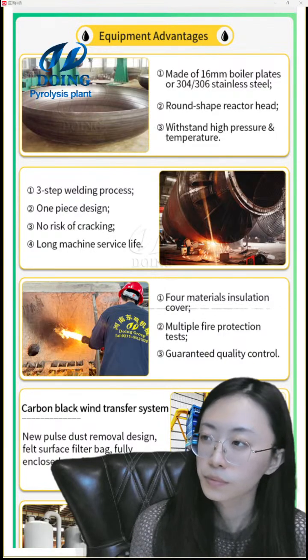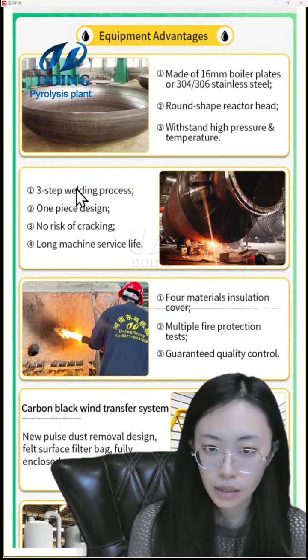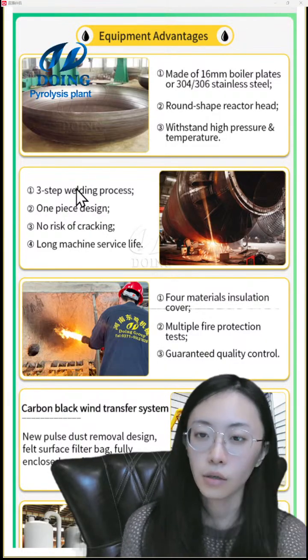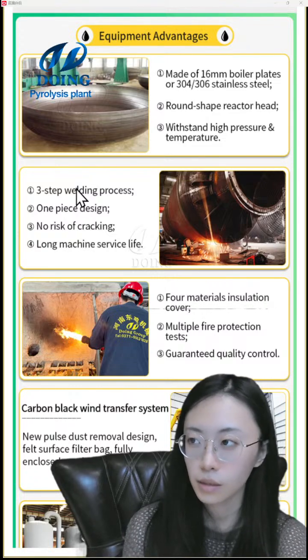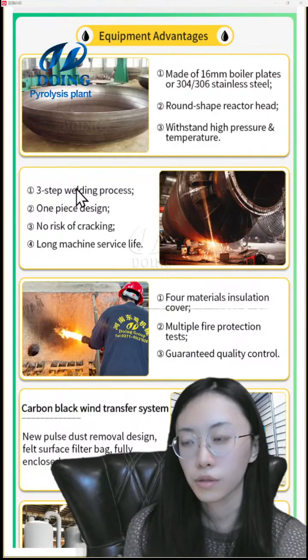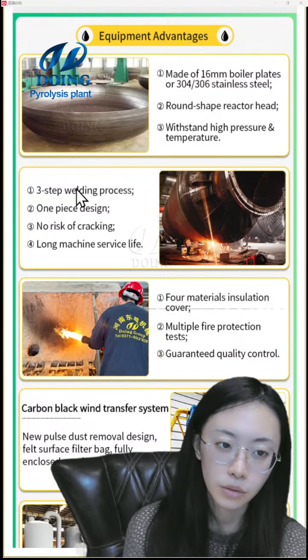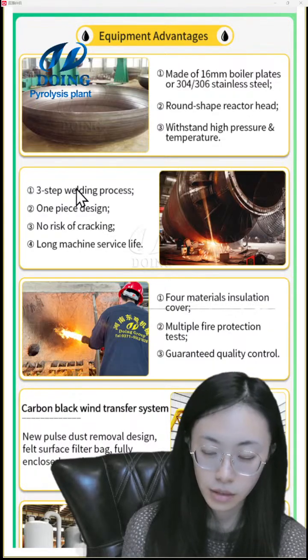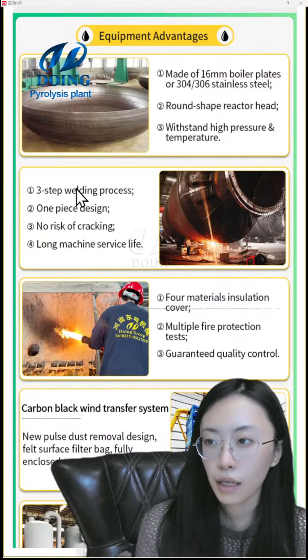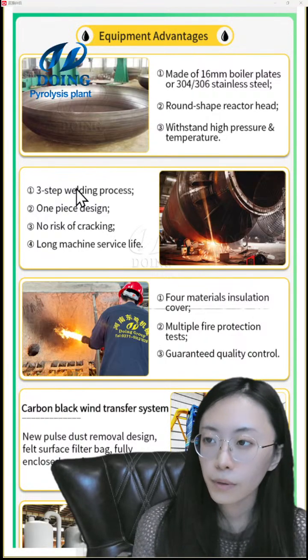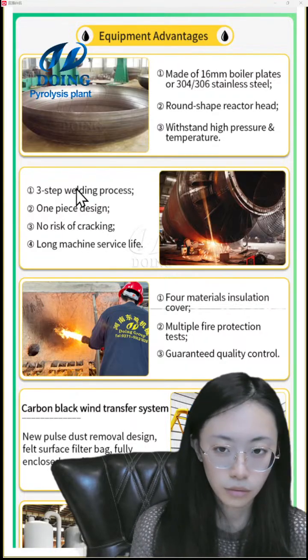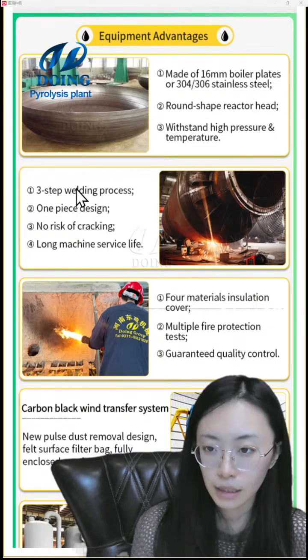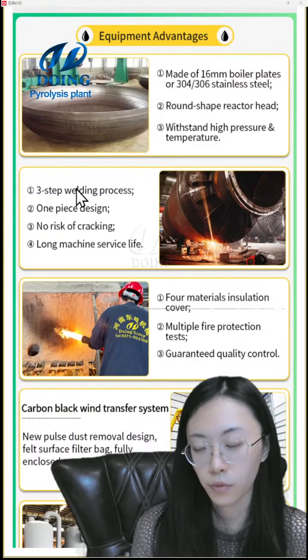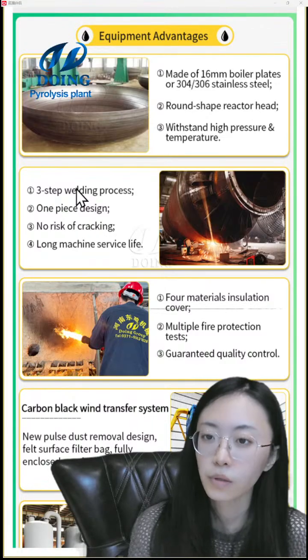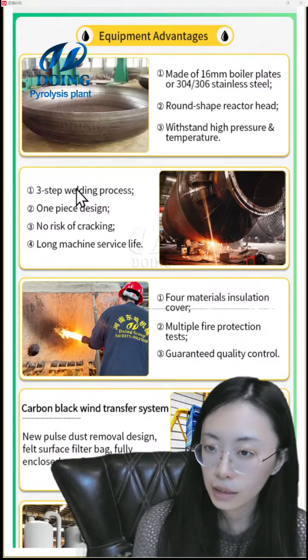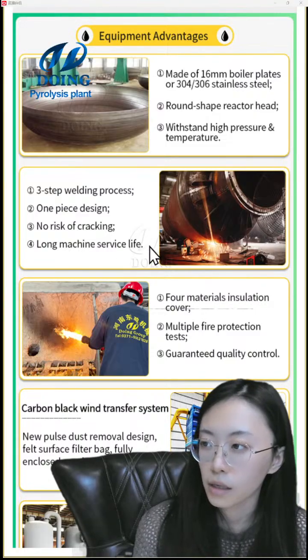Okay, and here is the welding process. We use machine technique to weld the reactor, which compared with labor welding is stronger, and can be used for the batch type pyrolysis plant. The reactor can be used for 3 to 5 years, and the fully continuous one, because we use indirect heating, can be used for 6 to 8 years. Why do we use indirect heating? If we use direct heating, like the batch type or semi-continuous, it will just damage the reactor in 45 to 60 days. So we use indirect heating, using the hot wind burner to send hot wind to the reactor. This is a one-piece design, no cracking, and a long machine service life.